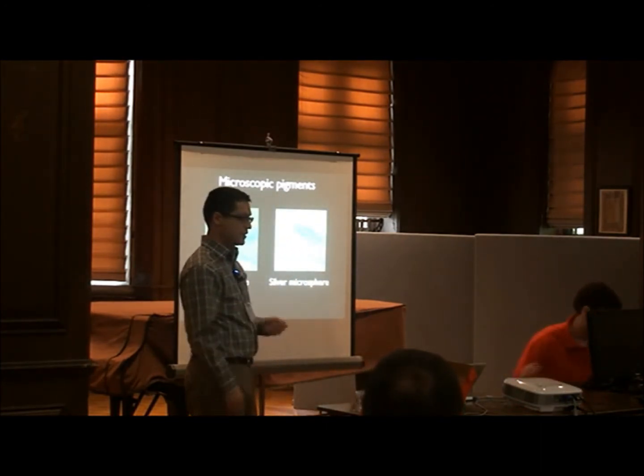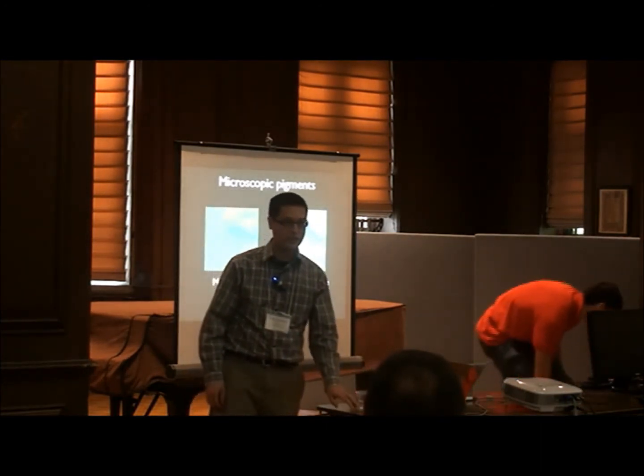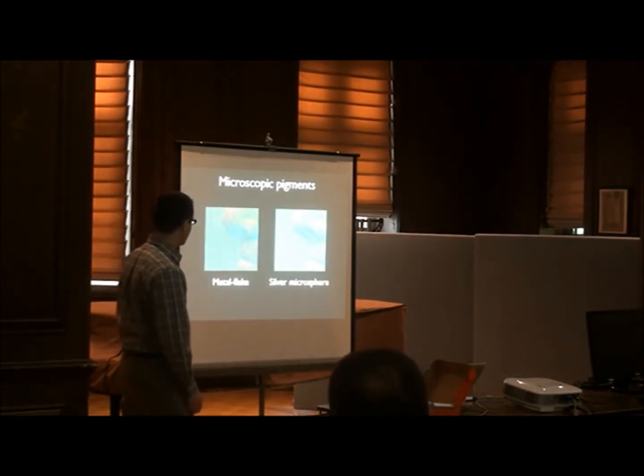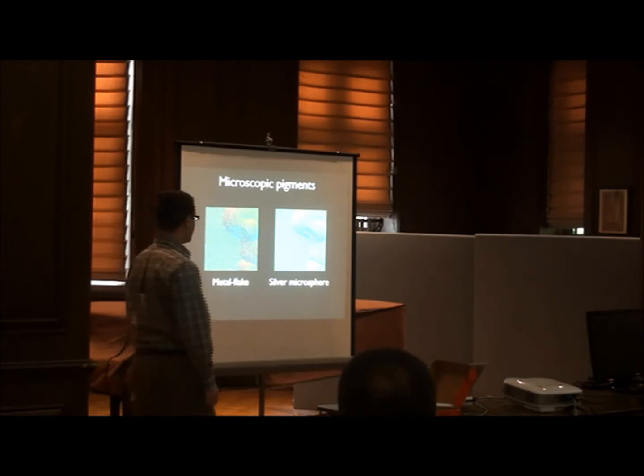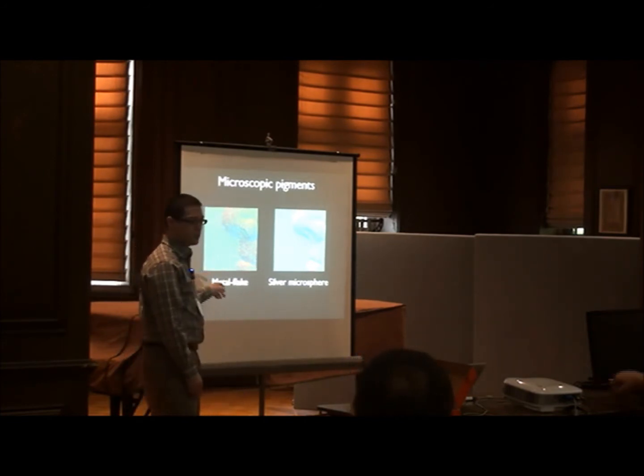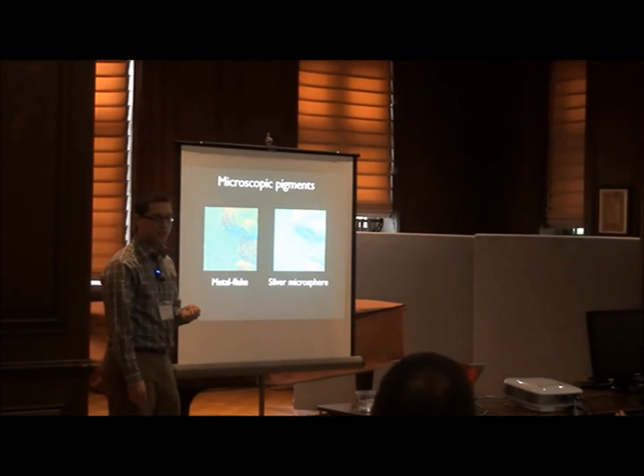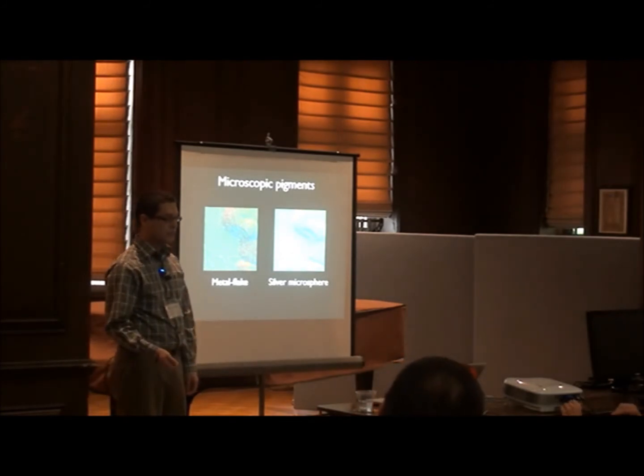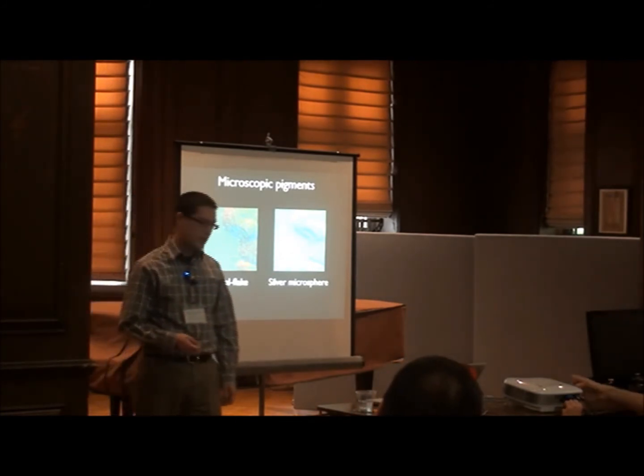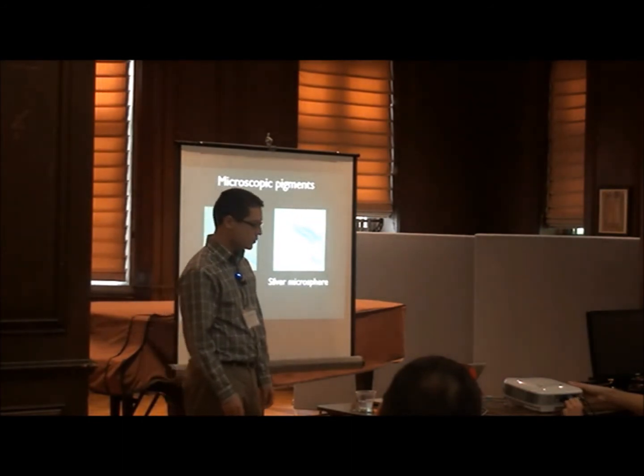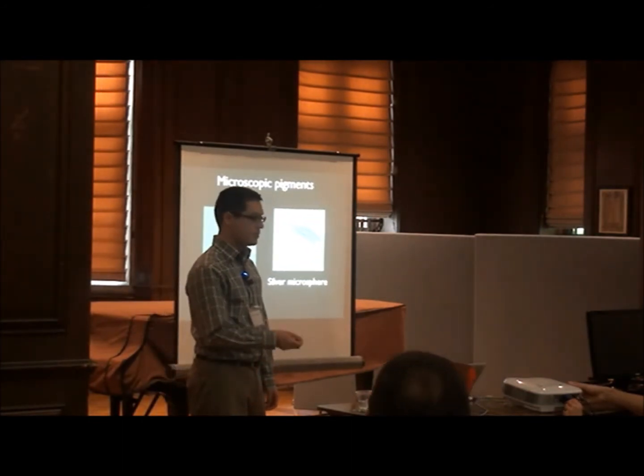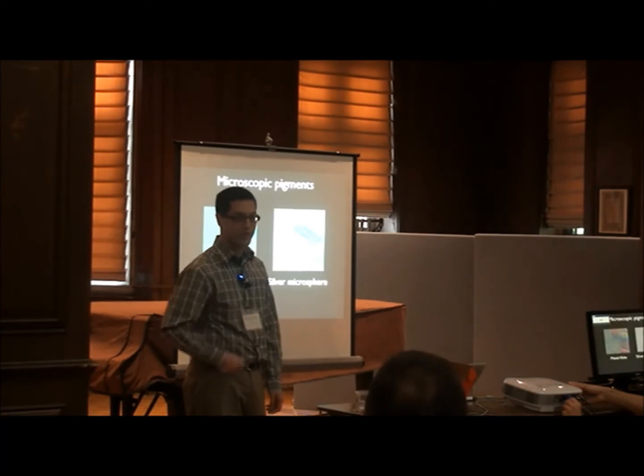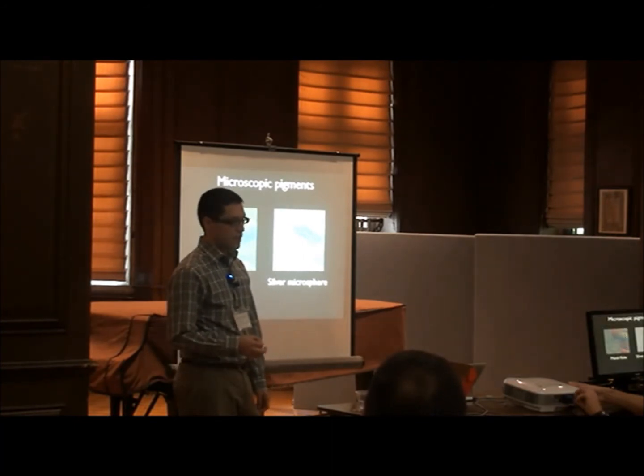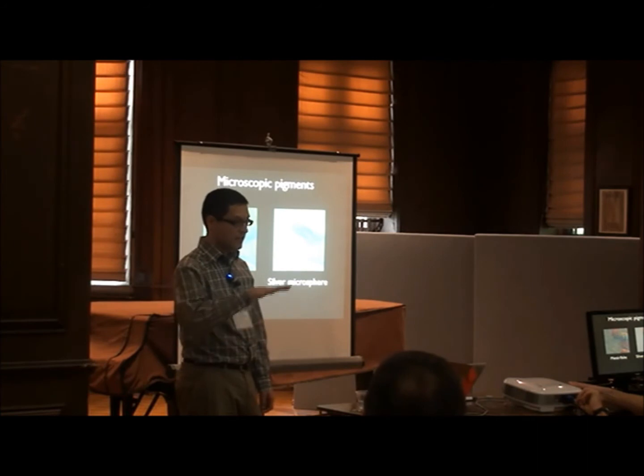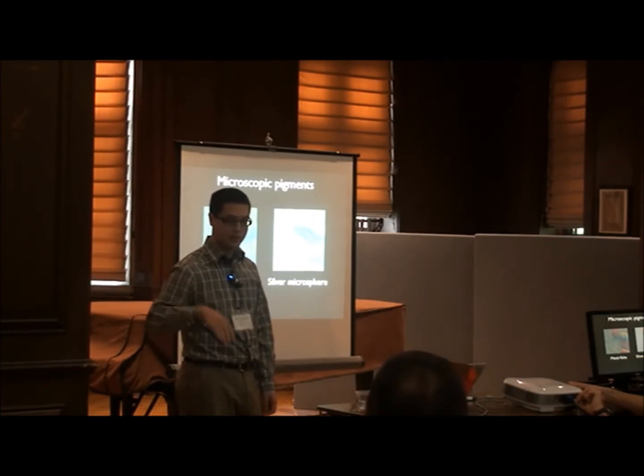One of the most dramatic improvements is simply improving the GelSight sensor itself. And here is the nose. I believe it's from a US dime. Our original system used a metal flake pigment that we made a reflective paint out of, as I described. You take some of those metal flakes, you mix them into some of the base material as a binder, and you airbrush it on. But those flakes were around 20 microns in size, and they act like little mirrors when they're embedded in that surface.